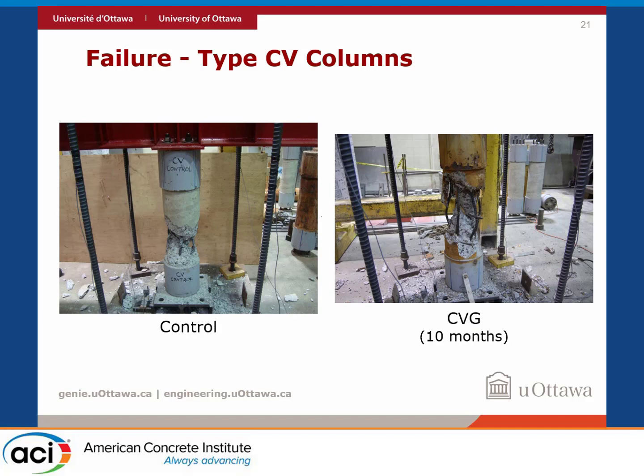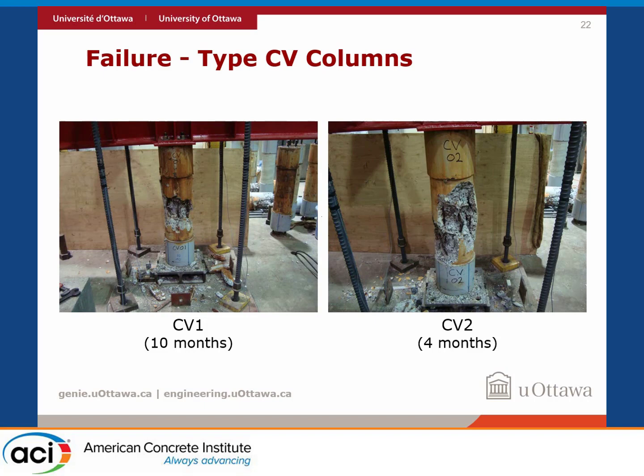These are pictures of the failure types of the columns. So you have the control one here for the longitudinal reinforcement. This one is the one where the entire cage was corroded after 10 months. So you clearly see the spirals rupturing and buckling of the longitudinal reinforcement. And these are the other two with longitudinal reinforcement corroded. Again, this also had a brittle behavior with buckling of the longitudinal reinforcement.